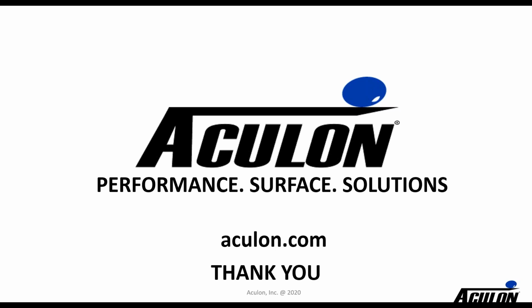Okay. Another question is, you mentioned that the thickness is only 2 to 4 nanometers. How do you control only putting down 2 to 4 nanometers? That's a good question too. It's really the fact that the treatment is self-limiting. It reacts with the surface, but not itself. So therefore, the only thing that's really bound is that first monolayer.